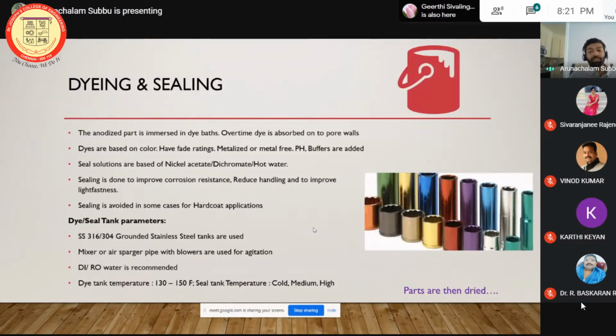After the anodizing, in the finishing step, we have the dyeing. The anodized coating is a porous coating. The dyes will enter into these pores, and that's when you get the colors. The dyes can also fade after some time, so it depends on the quality of the dye. If you use a very good quality dye, it has good light fastness, that is the ability to not fade soon. That is based on the dye quality. And you do this step after the anodizing step. Some dyes are metallized. They have heavy metals like chromium, which helps, but it's not environmentally good. So there are also metal-free dyes. And pH buffers are added to the solution to maintain the pH properly.